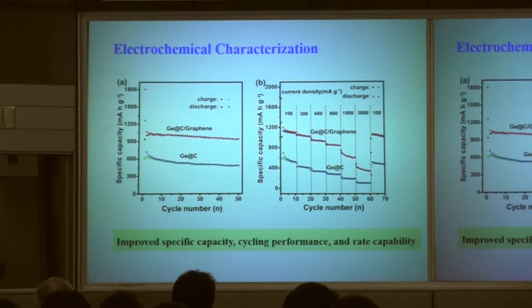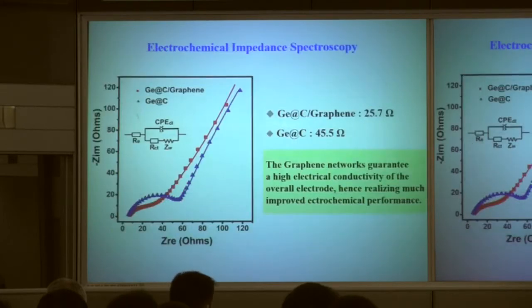We use these electrode materials and package a lithium-ion battery. You can see here is the cycle number. Here is the 50th cycle. Here is 70 cycles. We also measured several hundred cycles. You can see the stability is very good. Okay, if you use this composite material, the capacity is very high, near 1,000. Okay, and also the cycle lifetime is very good.